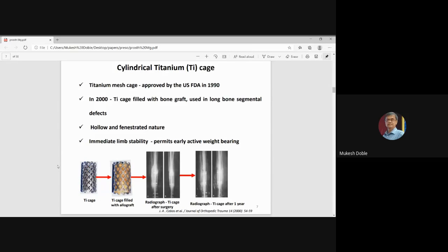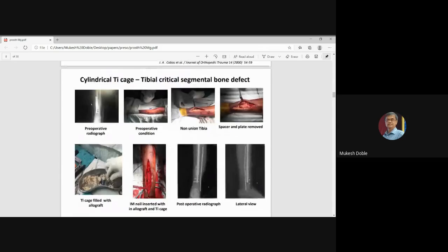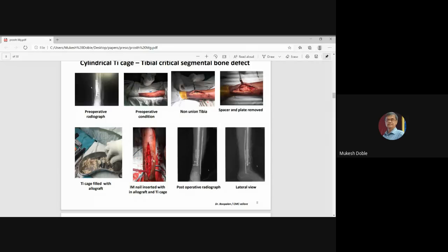It's hollow, mesh cage like, called fenestrated in nature. Immediately the limb gets stabilized, so the person can start using the leg, for example, and it improves the weight bearing capacity. You can see some radiograph pictures here, a fresh one, and after 1 year it starts improving immediately. Typically, this is how titanium is used: we have the initial pre-operative radiograph.